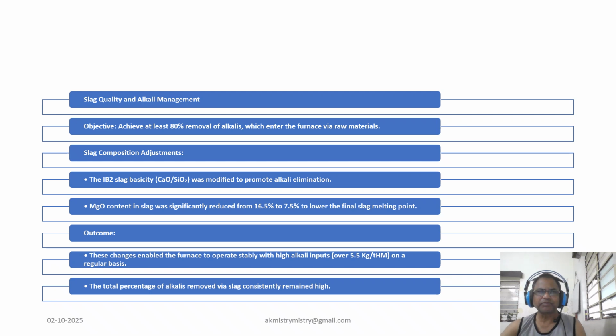Managing the high alkali content from the raw material was essential for a stable operation. The goal was to remove at least 80% of these alkalis through the slag. To achieve this, the team adjusted the slag chemical composition, as the slag basicity was modified to promote alkali elimination. A key change was reducing the MgO content in the slag from over 16% down to 7.5%, which lowered its melting point. This adjustment allowed the furnace to operate stably even with a high alkali input of over 5.5 kg per ton hot metal.